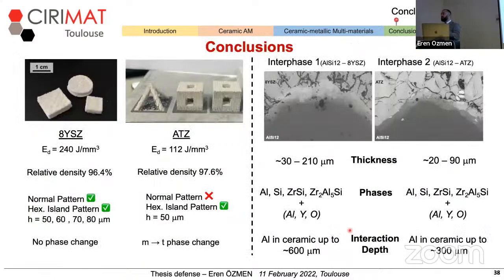So to conclude the entire presentation, I can say that 8YSZ and ATZ fabrication is like a game of compromises. 8YSZ has a larger application area and larger parameters that can be applied to the ceramic powder, for example, more lasing patterns, more hatch distance, and that kind of parameters. On the other side, we can apply a smaller parameter window to ATZ. However, with ATZ, we can obtain more complex shapes that we cannot obtain with 8YSZ.